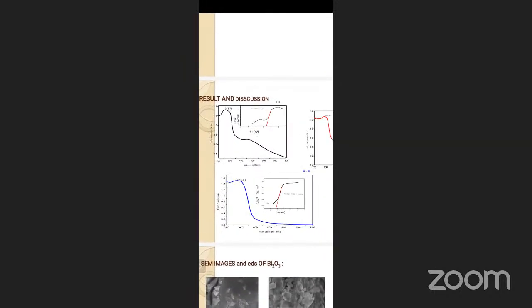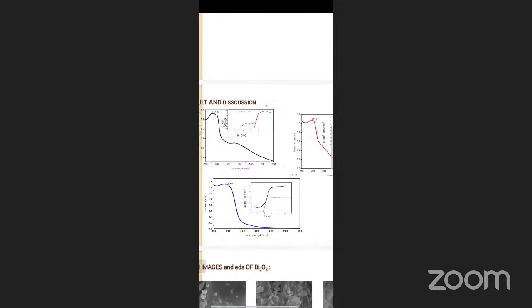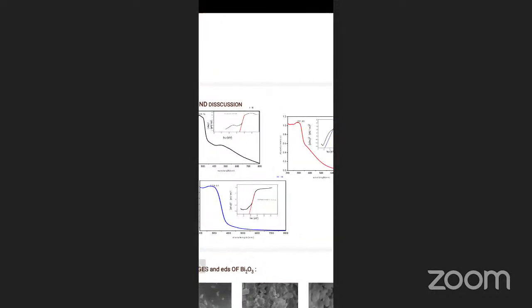Results and discussion: UV visible spectrum with the band gap. The absorption wavelength range of bismuth oxide is 230 to 400 nanometers. For the first sample, we get a wavelength of 265.76 nanometers with a band gap of 3.5 electron volts. The second sample gives 291.80 nanometers with a band gap of 2.13 electron volts, and sample 3 gives 278.01 nanometers with a band gap of 2.8 electron volts.